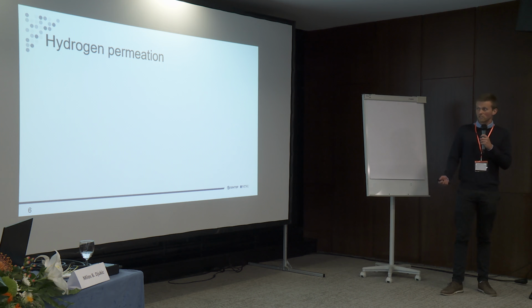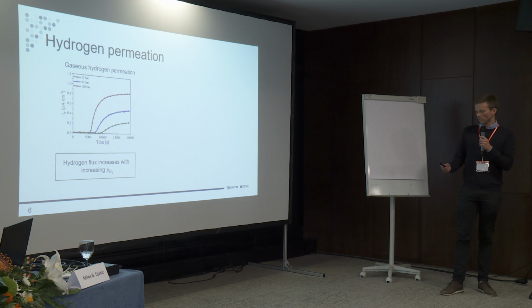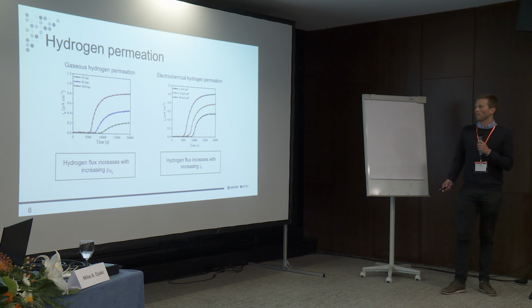So to the results, our hydrogen gas permeation looks like this. We have the permeation current density and the time axis, and we can see the 10 bar, 50 bar, and 100 bar curves. The steady state permeation current density, or flux of hydrogen, increases with the charging pressure. In the electrochemical hydrogen permeation results, we see similar trends. The hydrogen permeation flux increases with increasing charging current density.